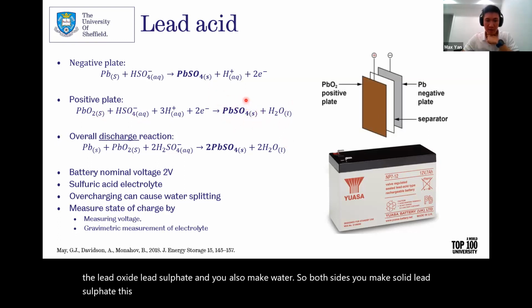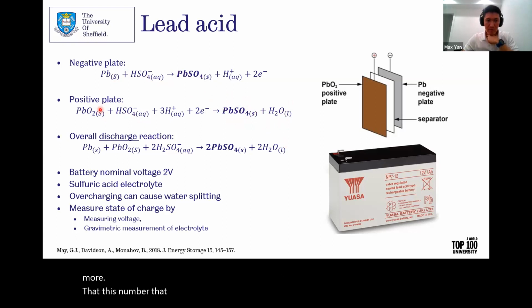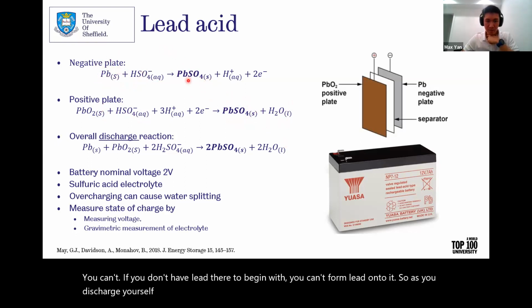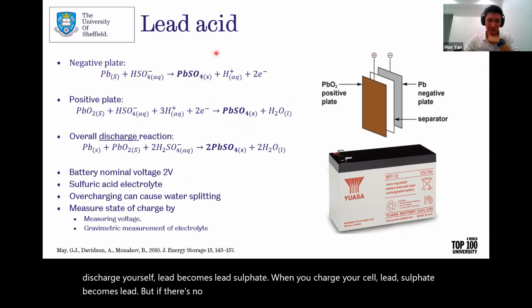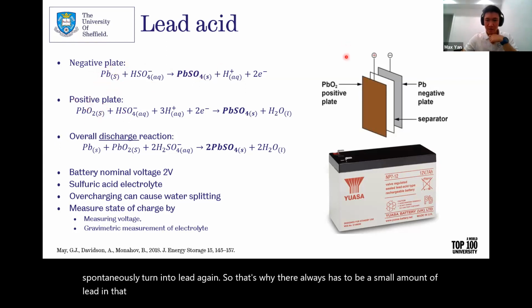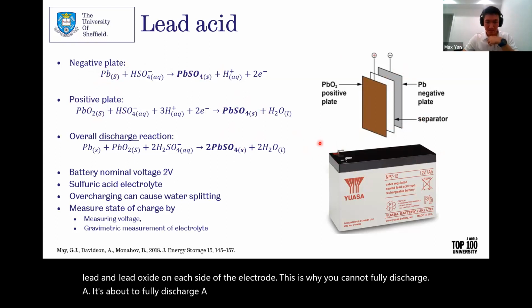This is why if you fully discharge your cell, you end up with lead sulfate. There's no more lead, there's no more lead oxide. But when you charge the cell, if you don't have lead there to begin with, you can't form lead onto it. So as you discharge your cell, lead becomes lead sulfate. When you charge your cell, lead sulfate becomes lead. But if there's no lead in the first place, the lead sulfate will not spontaneously turn into lead again. So there always has to be a small amount of lead and lead oxide on each side of the electrode. This is why you cannot fully discharge it. It's bad to fully discharge a lead acid battery.